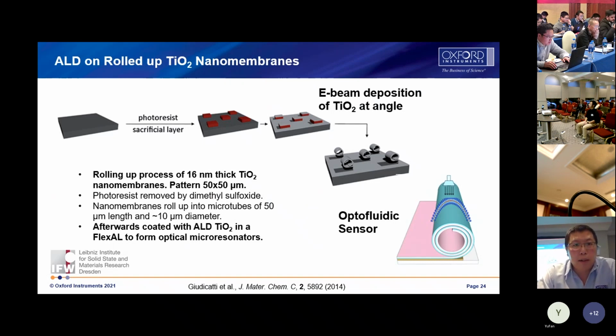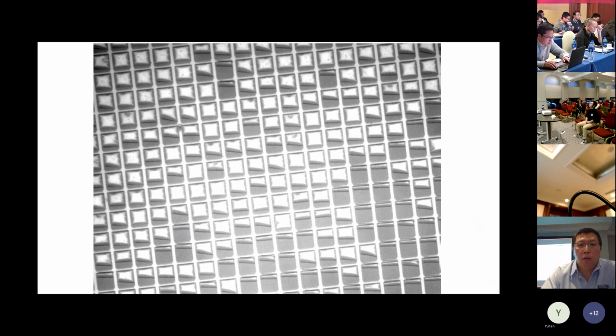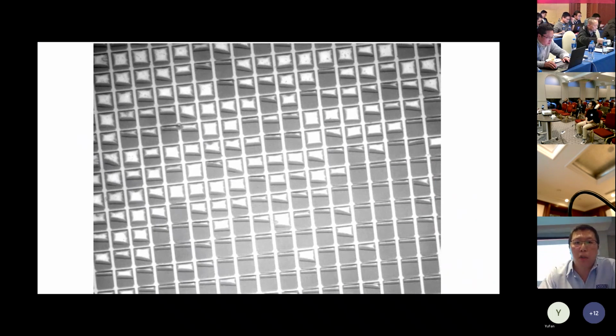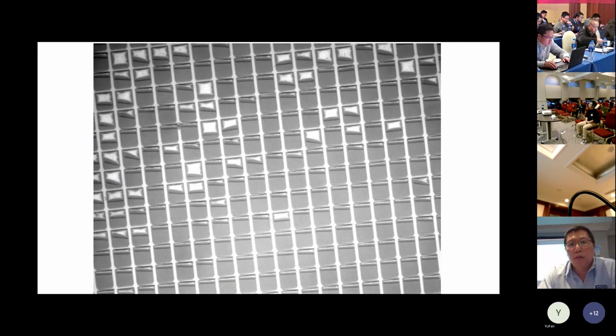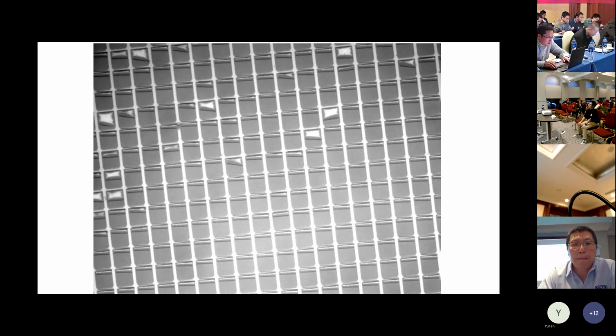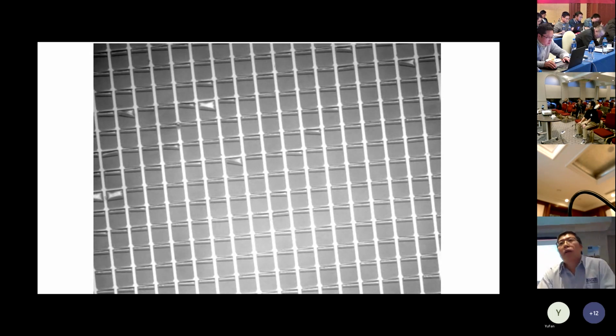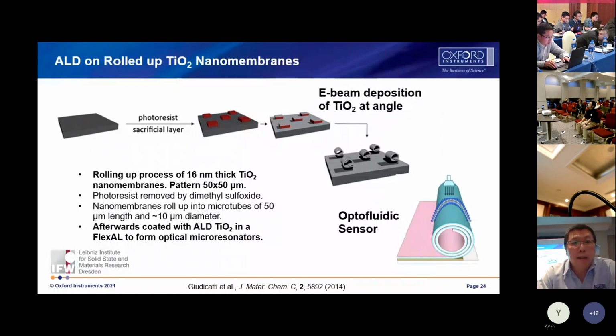This is another example, an optofluidic sensor made by rolling up 16 nanometer thick titanium oxide membranes, patterned 50 by 50 microns. Then the photoresist is removed, and the film rolls up into microtubes. Afterwards, it is coated with ALD for high quality titanium oxide. This is a small video showing the rolling up of the membrane into a microtube, 50 microns long with a 10 micron diameter. How thick is the film? The film thickness is 16 nanometers.